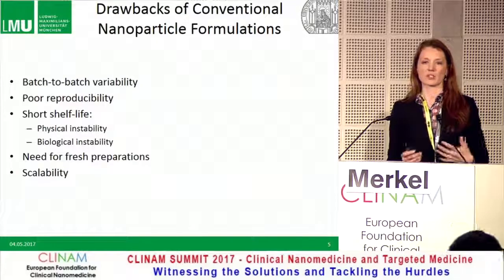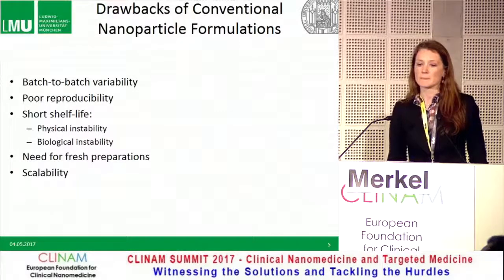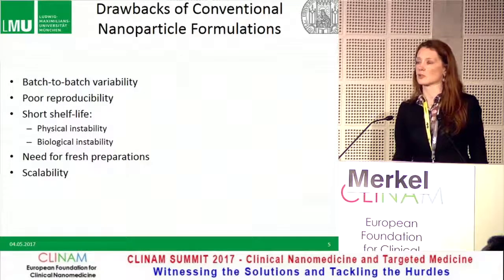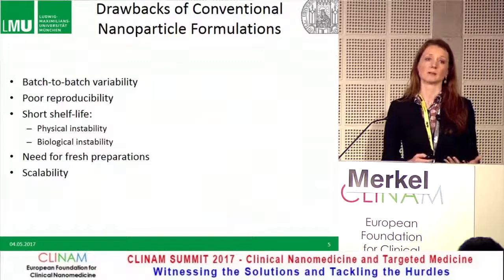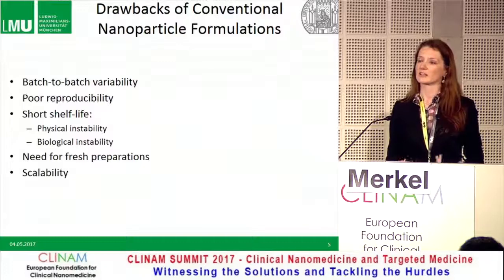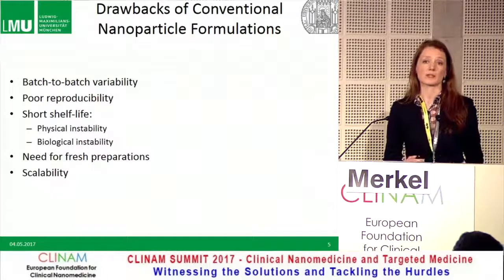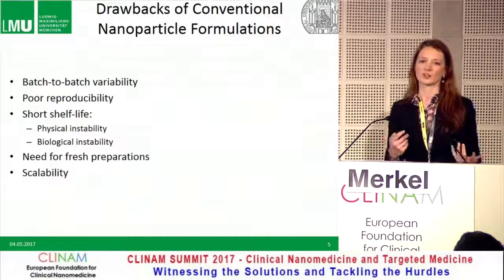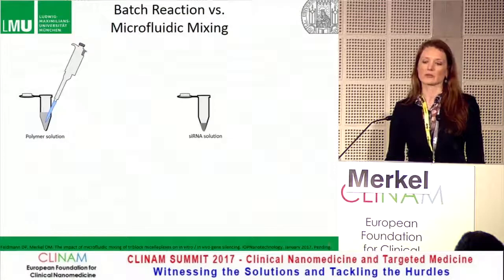With batch-to-batch variability we see poor reproducibility — different sizes between batches, and so on. Nanoparticles also have a problem of physical stability: they are not thermodynamically stable and tend to aggregate and sediment. If you want a nanoparticle suspension with a certain shelf life, this can be a problem, as is biological instability since nucleic acids are prone to degradation. In the clinic, fresh preparations would be needed each time, but it would be difficult to instruct a nurse to mix 5 microliters of this and 10 of that. So scalability is really important, and microfluidics is a great approach to this.